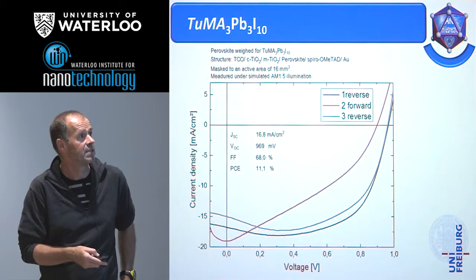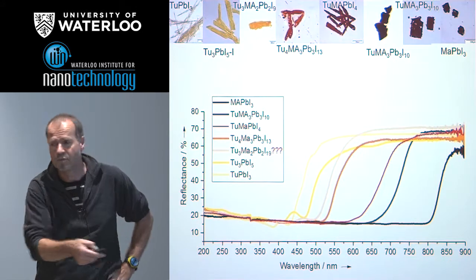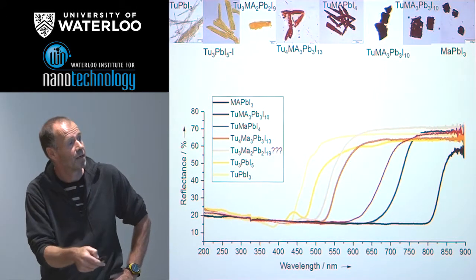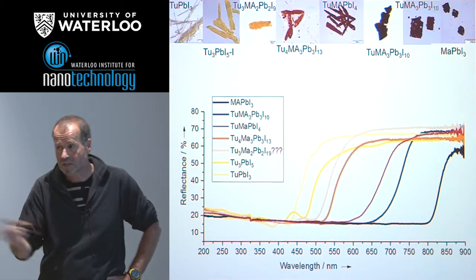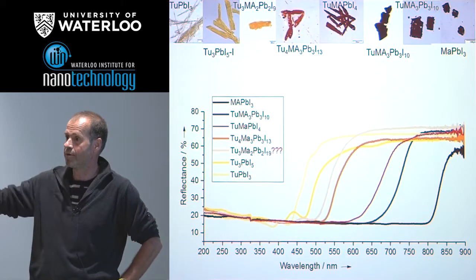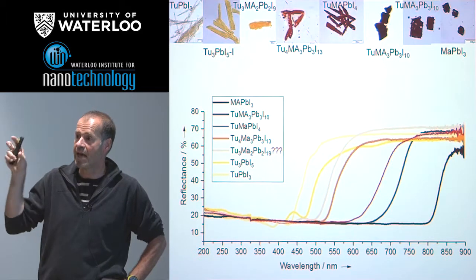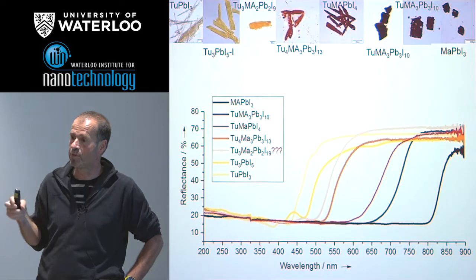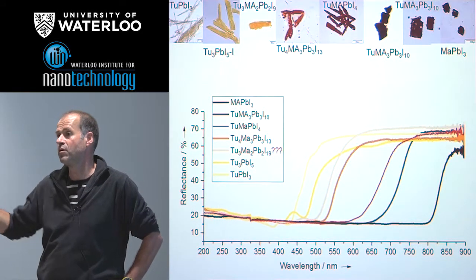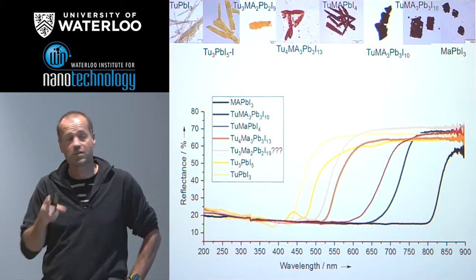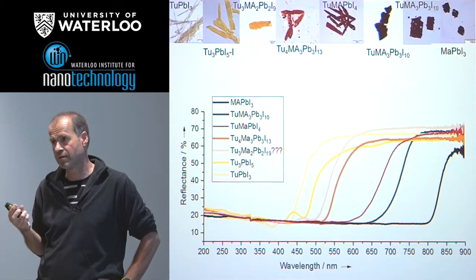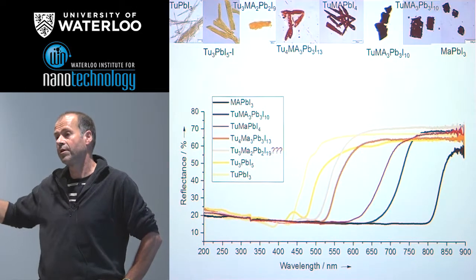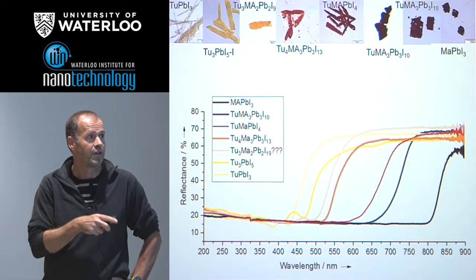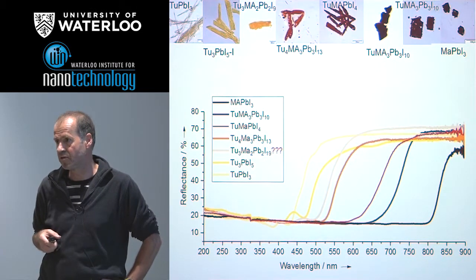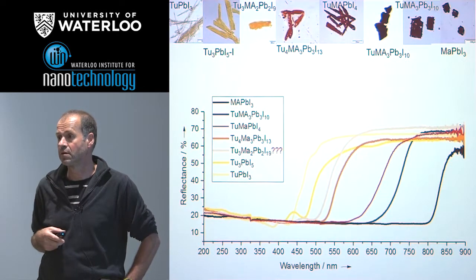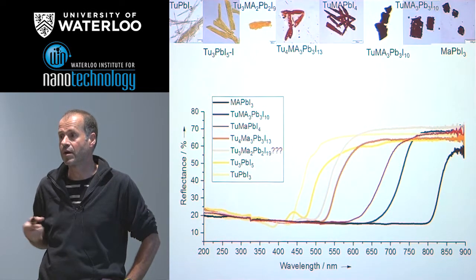And that's why we did all these optical investigations, because the optical spectrum is very sensitive. And we have shown for some other examples that we can obtain mixtures of both spectra if we have both compounds in our layer. So we have a quite good tool for the analysis of the really active layer by optical spectroscopy. But for that purpose, we have to fix it for a well-defined compound, so that we know which peak comes from which compound. That's why we do the detailed investigations on the crystal structures, to transfer this knowledge to the applied systems. I'm quite sure that well-defined two-dimensional systems are not the best material for an efficient solar cell. But we should know how it works to have an idea how we can influence the process.